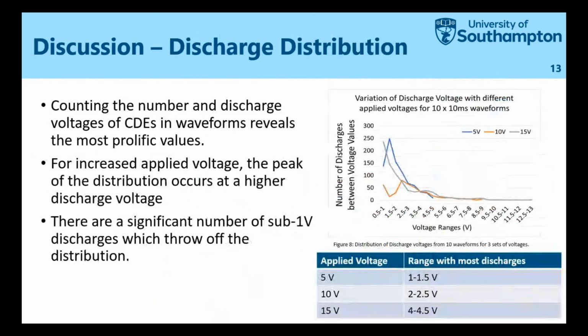With MATLAB, you can also count the peaks across multiple waveforms. In this case, I've counted not only the amount of discharges for 10 times 10 millisecond waveforms, I've also recorded the value of each discharge voltage, and seen what the distribution is. It follows a rough Weibull distribution. It's a little bit spiky because there isn't that much data, but with more tests I can smooth out the line a little.